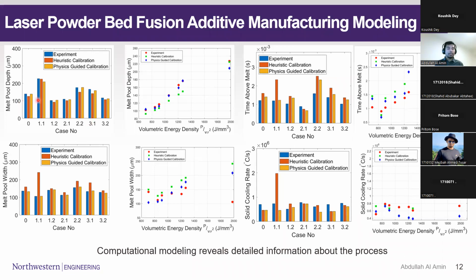And it looks like the experiment and the computational prediction do have a good agreement for both of those methods. In addition, not only looking at this bar plot, I tried to plot them against the volumetric energy density to see if there is a correlation or any hidden physics that we can reveal. What you can see is that this is mostly linear, meaning if I increase the amount of volumetric energy going into the system, my melted region would have greater penetration depth. That is useful information that I can leverage to manufacture a more quality product. So that's one thing.